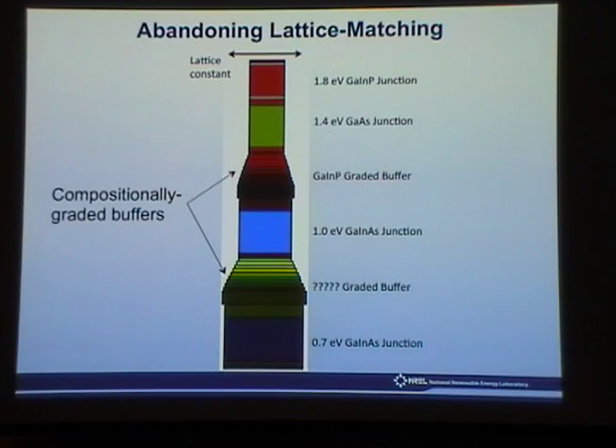Yeah. So why don't you use amorphous materials to avoid such lattice constant problem? And also, why don't you use the transparent conducting materials replacing those buffers? So in this situation, the second question is that they are transparent. The band gap of the gallium phosphide is 1.8 or so, 1.7. So this is in the orientation of the cell. So all of the high energy light is absorbed here, and then the 1.4 eV light is absorbed here. Once you get here, there are no more photons in the system that are 1.8 eV or 1.7 eV. So all of the photons that are passing through pass right through this material. So it is optically transparent to the light that's going through it.